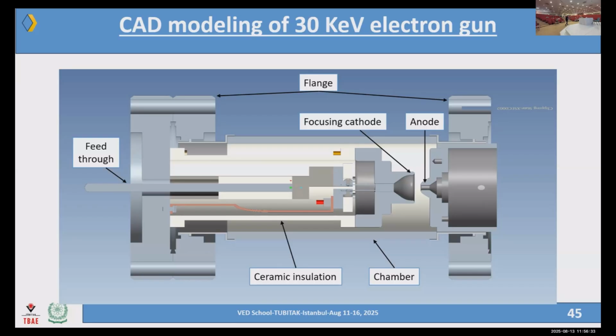It should not be degassing. It should not have pores. It should not be polluted. Otherwise, this guy is not going to work. Then you have micro welding here. You should provide your heater with a low resistance path in order to have uniform heating of this gun. Unless you have uniform heating, the Maxwell distribution is going to be disturbed, and the gun will not follow the model that you have assumed while designing it.